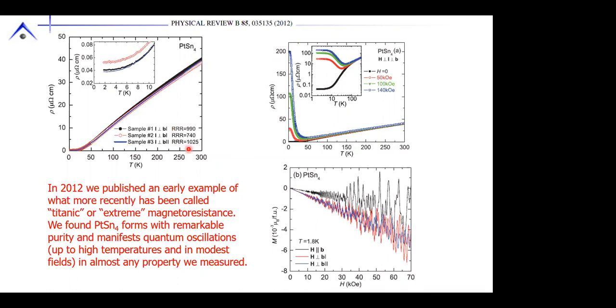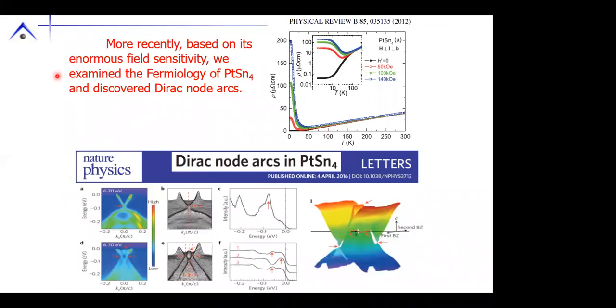Now, that's sort of cute, but what we found is in addition to this, it has phenomenal 500,000% magnetoresistance. It has quantum oscillations in almost any property you choose to look at, okay? So we were intrigued by this in 2012. As time passed, we started to realize, 2016, that in many cases, these extreme magnetoresistances could be associated with interesting topologies. And we went back to it. My colleague, Adam Kaminski, with his in-house laser ARPES, was able to find these hosted Dirac node arcs. Okay? And this is a material we sort of grew just as a desire to explore this unknown.